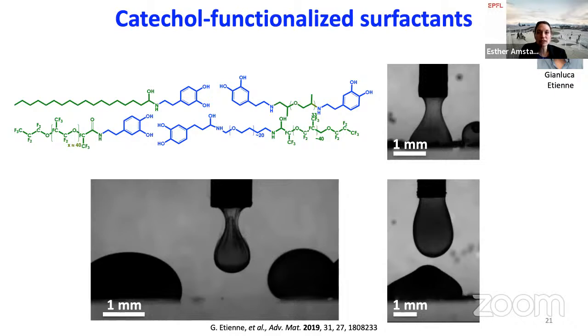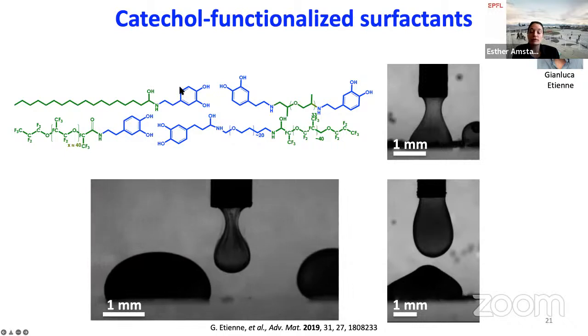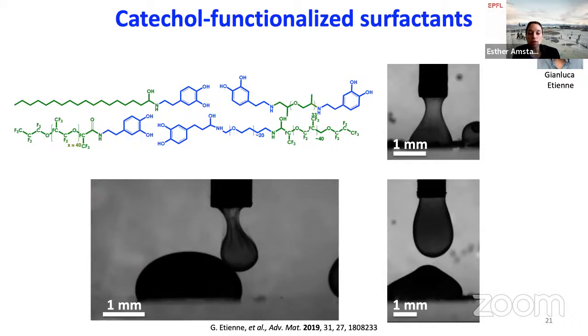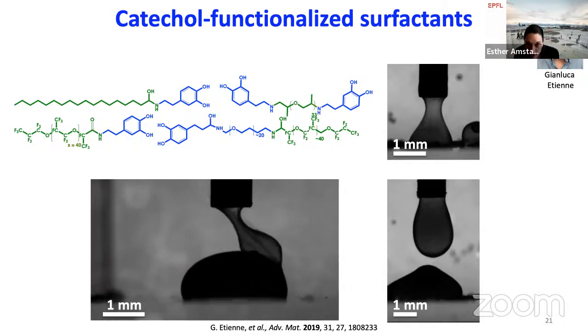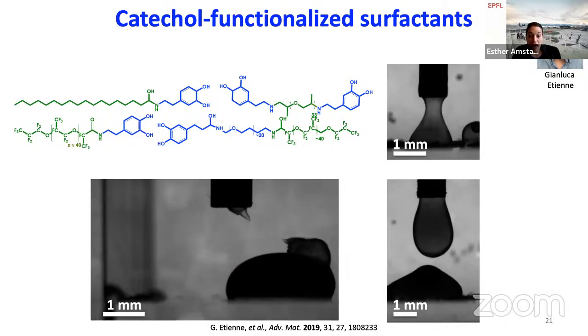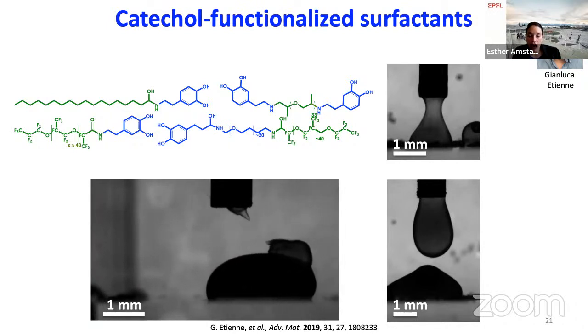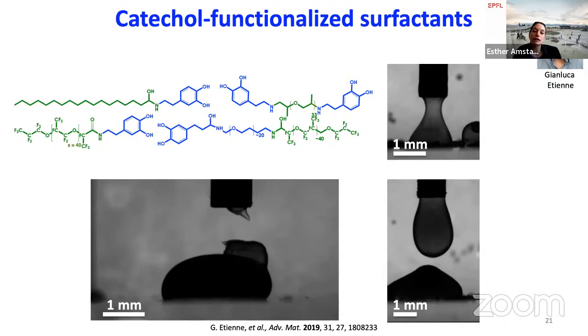And so to me, this is why we gave up a little bit this round, because I couldn't see how we can get the control that I wanted to get with this technology. But since we could get it with these functionalized surfactants, we pursued this route. And we actually looked a little bit further. We started to cross-link the shell with ions, with iron,